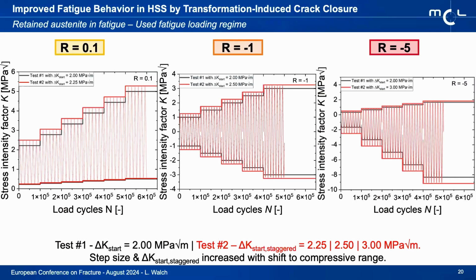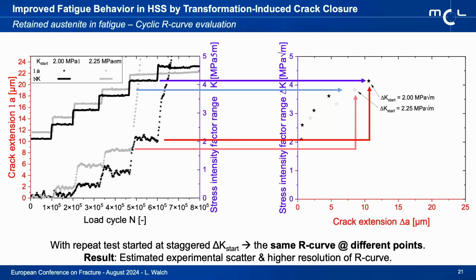So here you can see a basic load regime as we applied for pretty much all of our specimens. If you're wondering why the red line for the repeat test is a bit different from the first line, that's because we started at a different stress intensity factor range that was moved in the amplitude by half the step size here, so that we basically got improved resolution by looking at the same fatigue properties at different points.